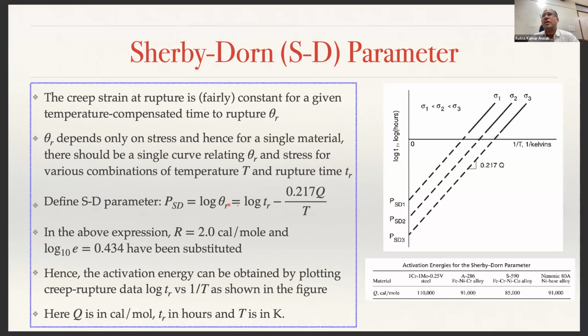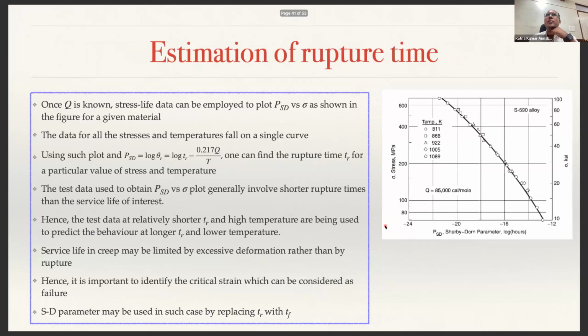The SD parameter is the logarithm of theta r, which is given by log t r minus 0.217 Q by T. So now if you plot log t r against 1 over T, with log t r as y and 1 over T as x, then the slope m is 0.217 Q. And if you extrapolate that line, that will give you the log t r, which is what you call the rupture time. You can compute the rupture time. That is how you can calculate the life that is available for a component.